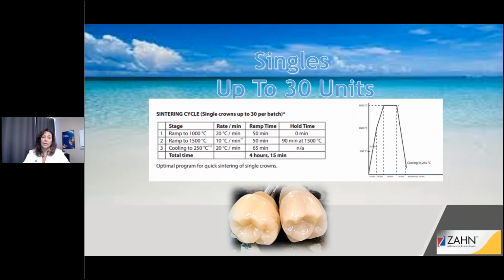But if you overfill the furnace and you're sintering too many units at once, they're not going to absorb the heat the way they need to in that short 4 hours, and you're not going to get a desirable result. So it's a great program, but it is important to follow the instructions and not put in more than 30 units. Typically, I'll do 1 tray, and that works out great.